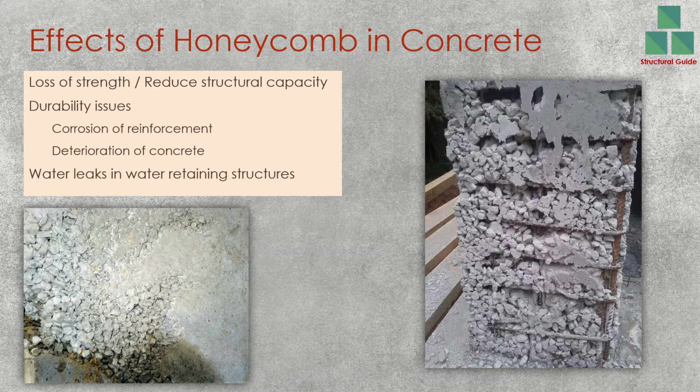Durability issues. Corrosion of reinforcement, deterioration of the concrete could occur. When there are cavities, when there is porous concrete, through these pores or cavities, oxygen and moisture can reach the reinforcement, and then reinforcement corrosion may occur.